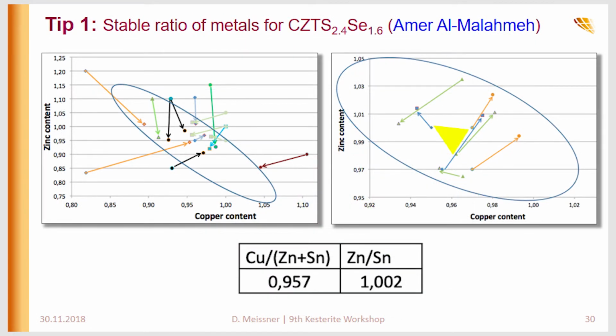Just a remark to the composition. We work with thermodynamically stable compositions, of course, and they are not always what we put into the ampulla. Of course, as Susan has shown you, you can vary the composition on a wide range, but then if the composition is not the final composition, in the formation of CZTS, you also form secondary phases, which means other compounds, zinc sulfide and tin sulfur selenide and whatever, lots of secondary phases,